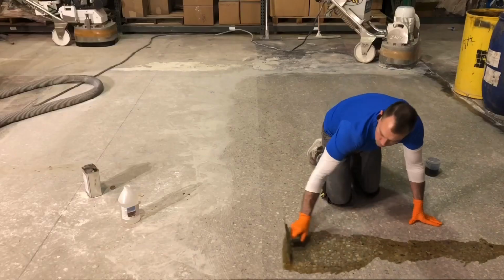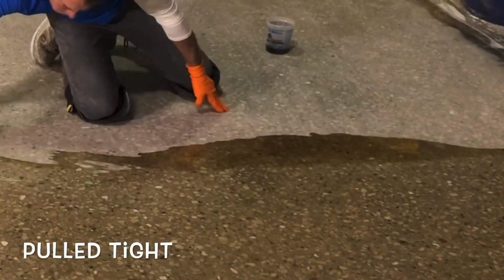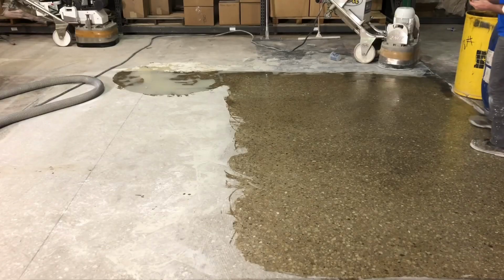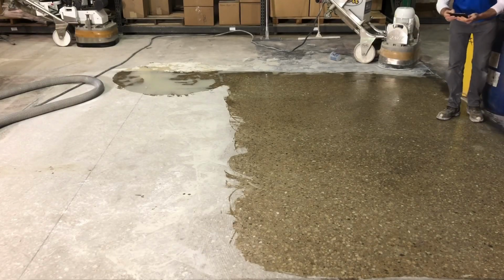Once the floor was clean and dried, it was then decided to use a urethane grout step, and the reason being is because there was still a small amount of porosity, so the floor would benefit from that extra step of urethane grout. The urethane was applied pure using a straight trowel. So it's just a tight skim, and again, the whole goal is just to fill in the microporosity or the small holes.